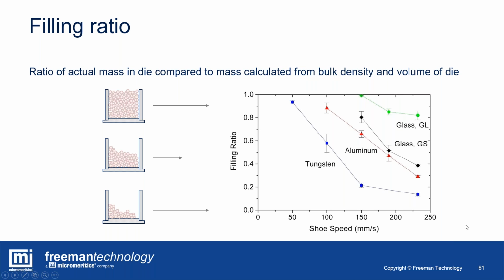And you can see the x-axis here represents that shoe velocity relative to the die, 50 up to 230 millimeters per second. And you can see this fill ratio, the y-axis, 1.0 represents 100% full, and of course we can measure the mass of the sample. We know the density after the pass, so we can accurately define or verify how much material was deposited in the die after the shoe passed across the top for a given speed.